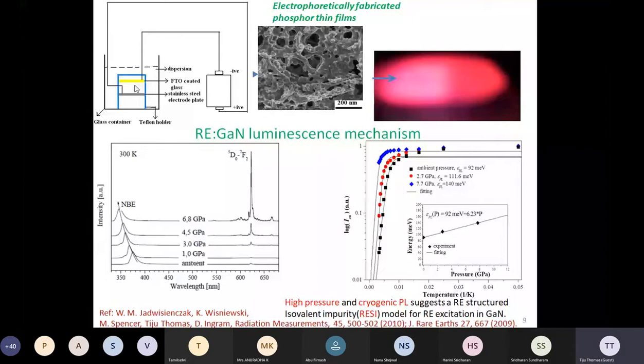So here, using these particles of nitride that were pounded together, that was ball milled and as a consequence made very, very tiny, they were dispersed in this bath. So you were able to disperse them, and you have to stabilize it, make a stable colloid, something like milk. If your milk is rendered unstable, you squeeze lemon inside your milk, it becomes curdled, right? It's exactly the same. And if it is curdled, you can't use it for making tea. It's something analogous here. So the colloid has to be stabilized so that you can use it for electrophoresis. Okay? So you have stabilized it, use it for electrophoresis, you get these very nice deposits, and then the device structure I showed you is what was realized, and this fantastic red emission is observed.